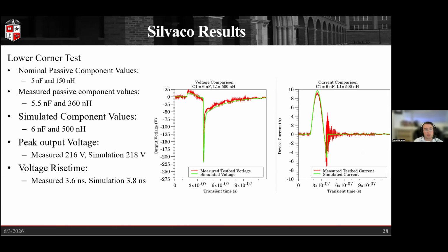And so with this, we started looking at the lower corner. And so as I mentioned, we had the various ranges of capacitance and inductances. And so with that, the lowest corner was our lowest inductance and lowest capacitance value, that being 5 nanofarads nominally and 150 nanohenries nominally. Measured, they came in a little closer to 5.5 nanofarads and 360 nanohenries. And when we actually simulated it in order to get the curves to match relatively well, as we can see through these characterizations, we ended up needing 6 nanofarads and 500 nanohenries. So again, within some reasonable margin of error when we're talking about relatively small inductance values and capacitance values.